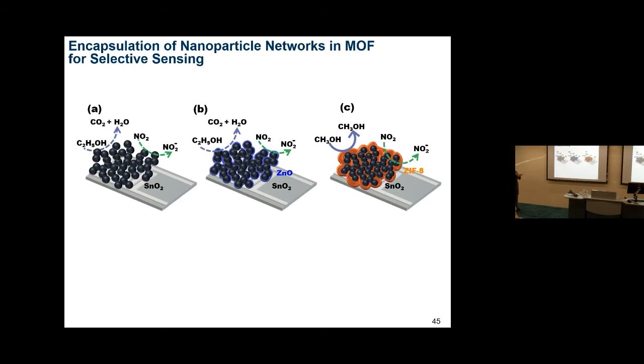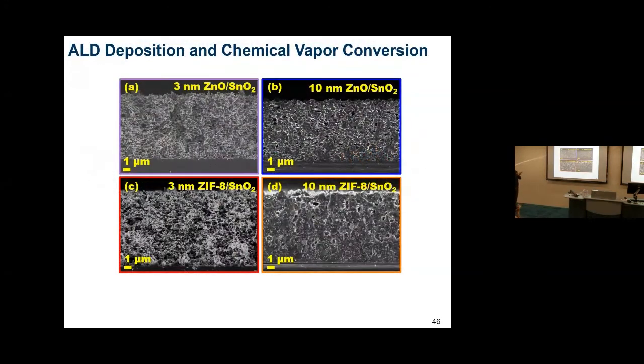We tried to compare what happened if we coat our zinc oxide, our tin dioxide sensor, with something like ZIF-8 or another MOF. The way we do it is by ALD deposition of zinc oxide on a tin oxide film, and then we convert it by chemical vapor conversion.